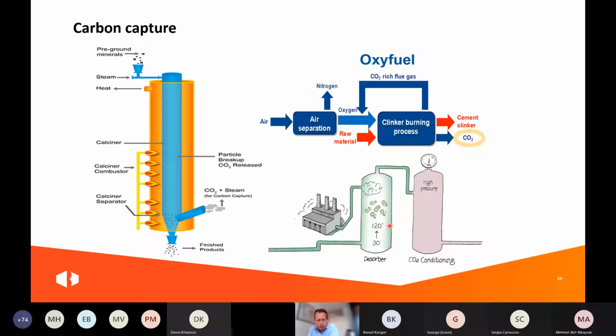Oxyfuel, for example, is not using regular air in the kiln, but using pure oxygen in the right amount, sufficiently to burn the fuel. So you will end up with a very high CO2 concentration at the end of the kiln. And the left system is a separate calcination of the limestone, so you will have pure CO2 from the limestone. Of course, in that case, you are going to miss the CO2 that's released by the burning of the fuels, but in any case it will capture about 60% of the CO2.